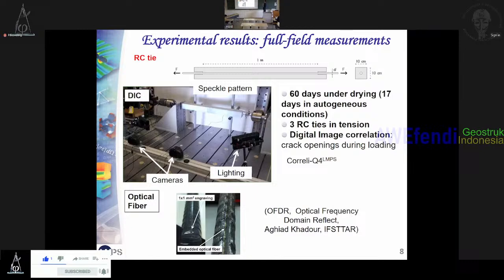Of course, it will depend on the rigidity of the machine, but here we have a cell to measure the evolution of force, and we also have an LVDT sensor, and we use digital image correlation. So we have the boundary conditions, and we are not using information coming from the loading frame. It can be important, for instance, in bending, or perhaps also for stability of the crack. But here it's reinforced concrete.